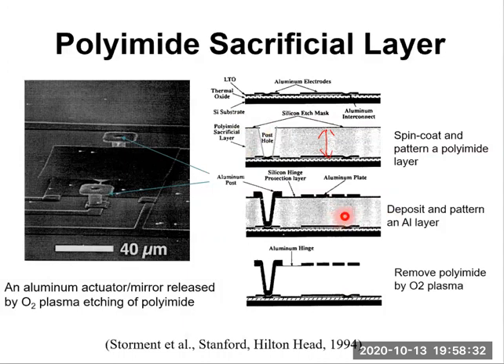Next, deposit and pattern an aluminum layer. Okay, so the aluminum layer is deposited and patterned. Note that this aluminum is deposited inside the post hole to form the post structures. As we can observe in this SEM image, this freestanding mirror is supported by these two aluminum posts.